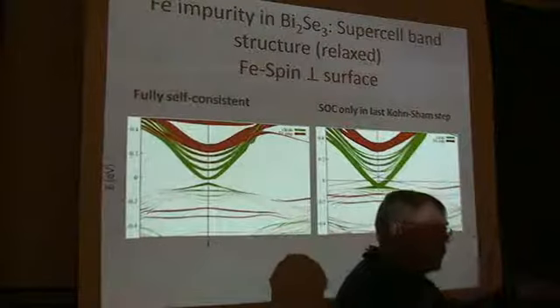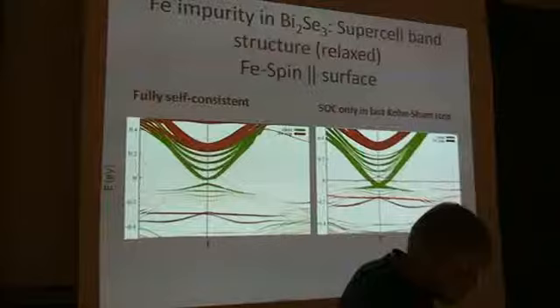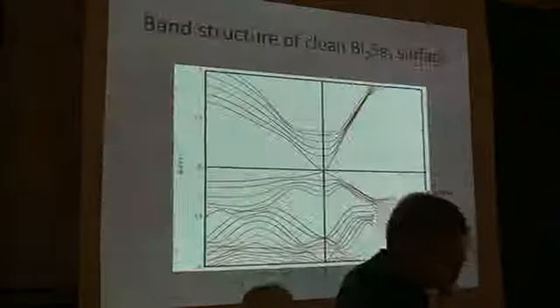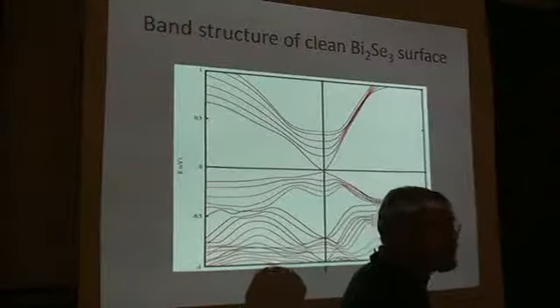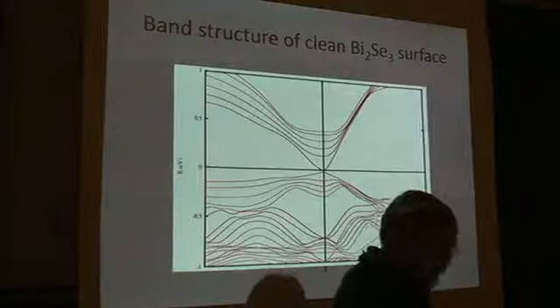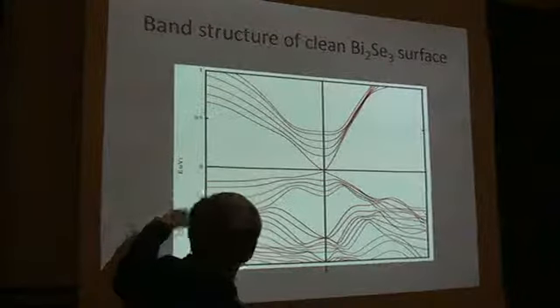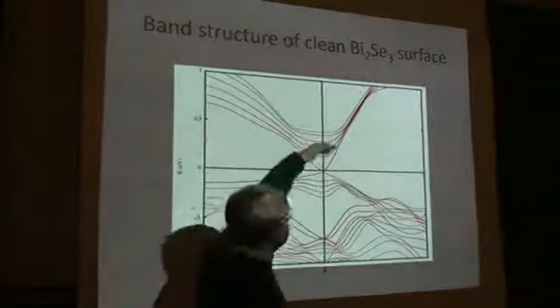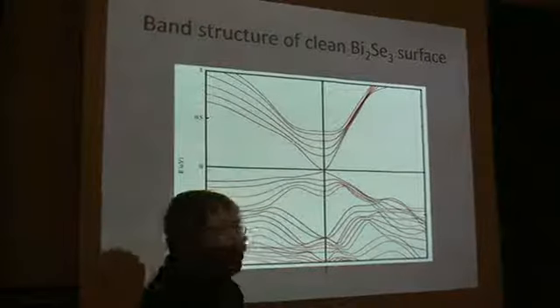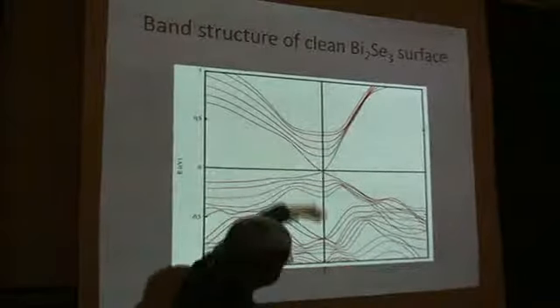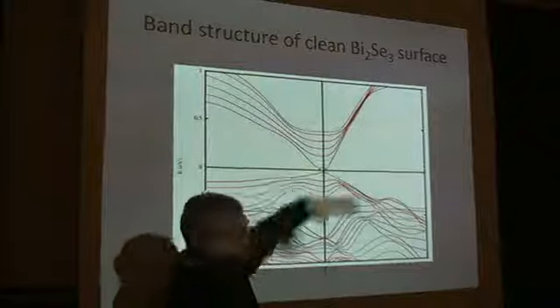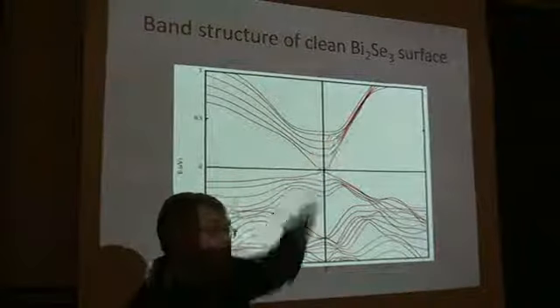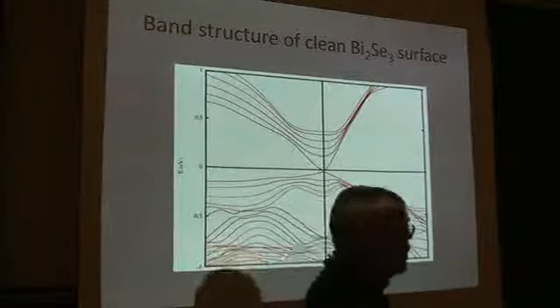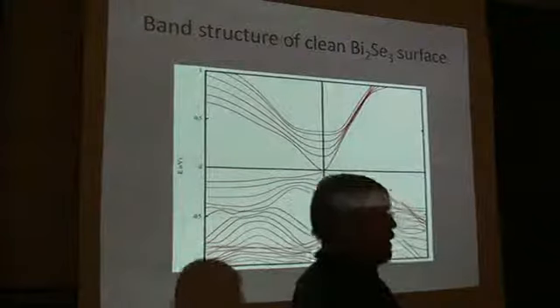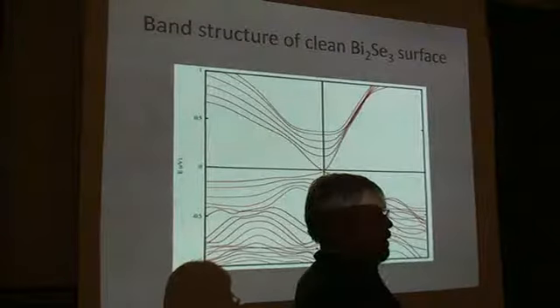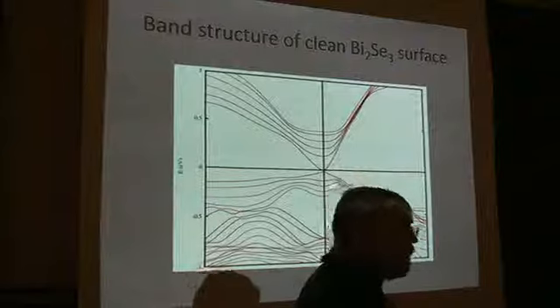But basically, if you sum over all k states for the band structure, the problem here is that we have to look at a small enough system because of the impurity. But if you take pristine bismuth selenide, the chemical potential will be somewhere, I forgot where, somewhere up here, and the Dirac point will be 0.3 electron volt below. But you can see that the states below the Dirac point are flatter, so they will correspond to a larger density of states. So is the Dirac point particle-hole symmetric close to the point or not? Sounds like it's not from the picture. No, it's not. So that's what I'm saying.